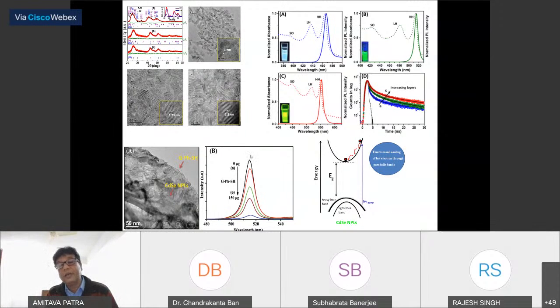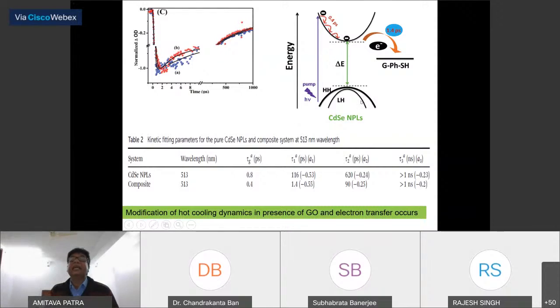In presence of graphene oxide, we have seen that PL intensity decreases because you can extract that hot electron from the 2D structure to the graphene oxide, and you can generate an electrical current. So here we have absence of the graphene oxide. This hot electron relaxation takes 0.8 picosecond. But in presence of graphene oxide, it goes down to 0.4 picosecond, and the electron transfer rate is 1.4 picosecond to the graphene oxide. That means electron you can separate from the 2D structure, and this you will generate a photocurrent.